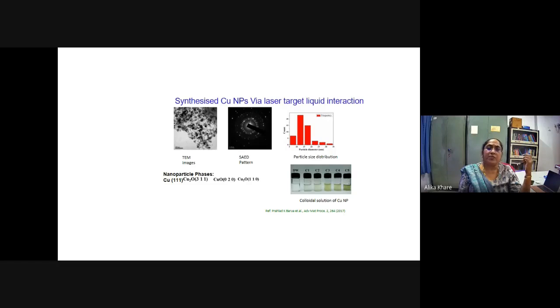This is the synthesis of copper nanoparticles. Here the target we used was pure copper, and it was dipped, or immersed, into water. Since copper is quite active and interacts with oxygen, when we immerse it into water and focus the laser, water molecules also break down to give us hydrogen and oxygen. And this copper and the copper ions interact with that oxygen, so they form cupric and cuprous oxide also.